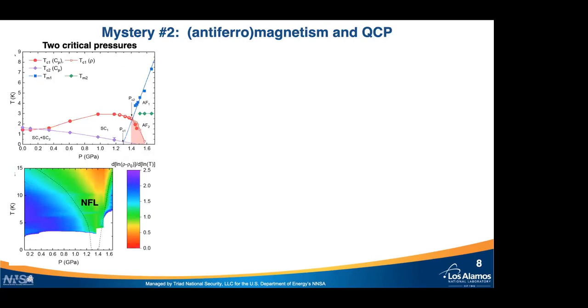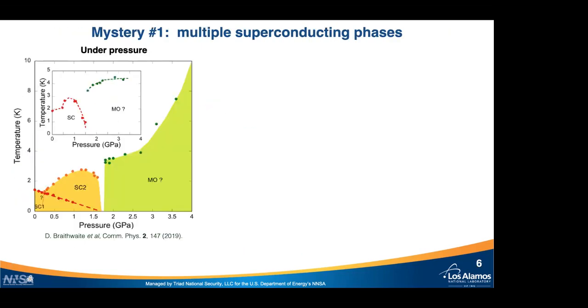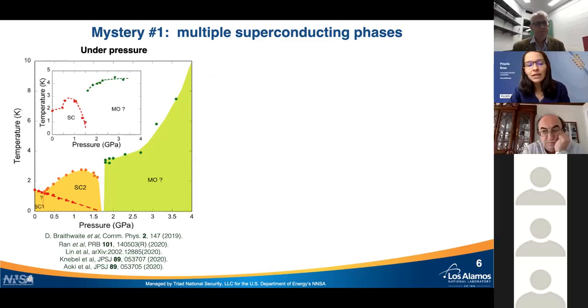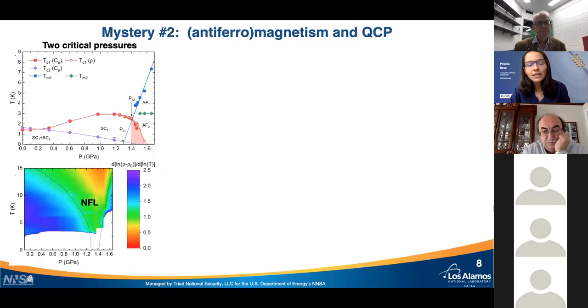And again, we're not the only group to apply pressure to this material. There is always a kink at 0.2, and above this kink, one transition goes up and the other one goes down. That is extremely robust. Three different groups observed that. I should mention that compared to this result, I think we did go a step further in the sense that we were able to look at this region around 1.5 GPa and really see this coexistence region. But I would say the results under pressure are fairly reproducible.